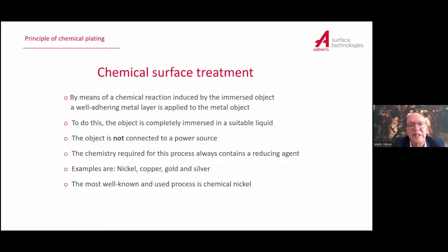The second group is the chemical surface treatment. By chemical surface treatment, I mean that, by means of a chemical reaction induced by the immersed object, a well-adhering metal layer is applied to the metal object. It means that when I have a bath, a tank filled with the solution, I take my part and put it into the bath, and that part starts a chemical reaction in the bath. Due to that reaction, the nickel or silver or copper is plated onto the part itself.